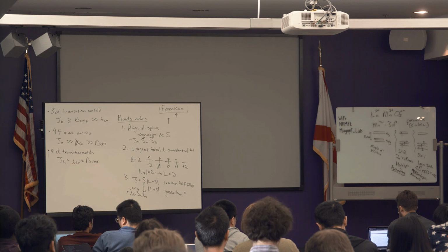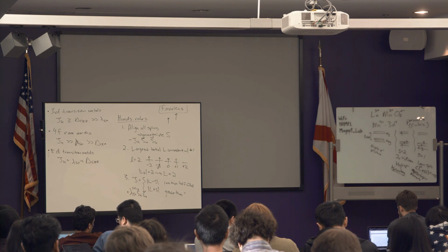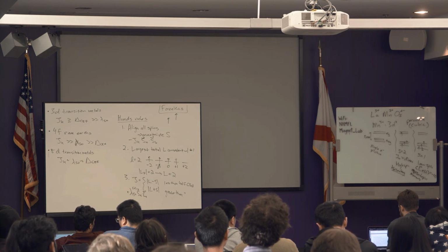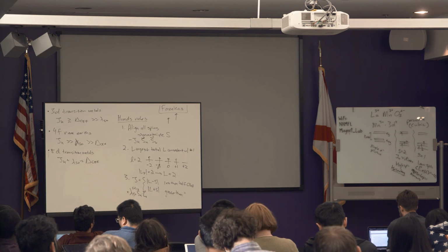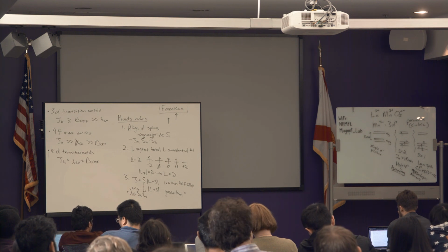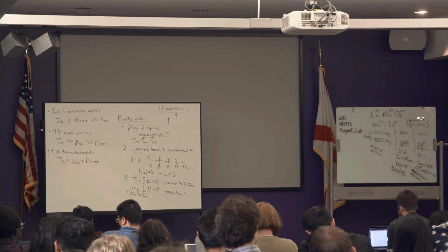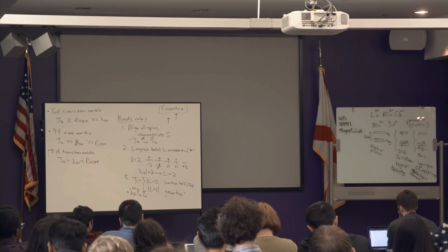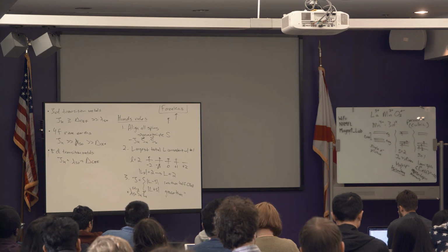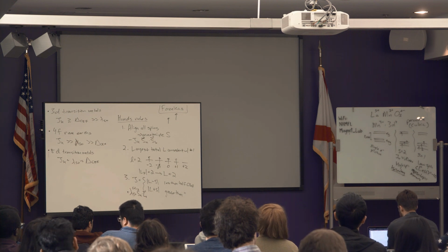I actually get a doublet, which has 2 states which are the time reverse of one another. And what's interesting about this doublet is that it's an Ising magnetic doublet. So you can see that you're definitely going to have some expectation of Jz, but if you try to find your expectation of Jx or Jy, there you need something that's connected just by a change of delta J of 1.